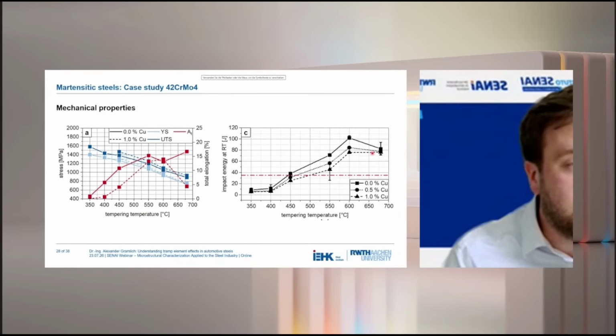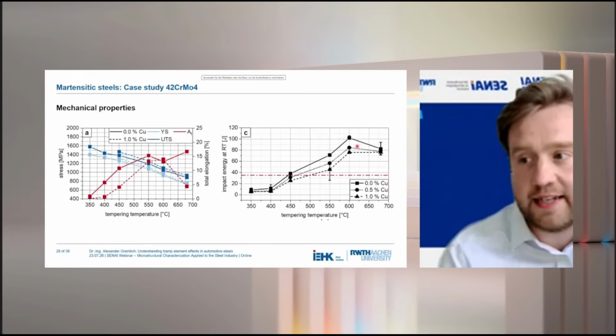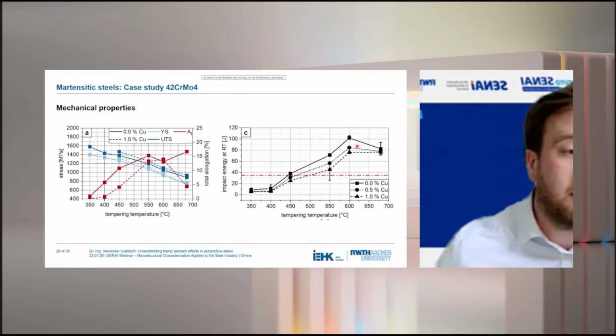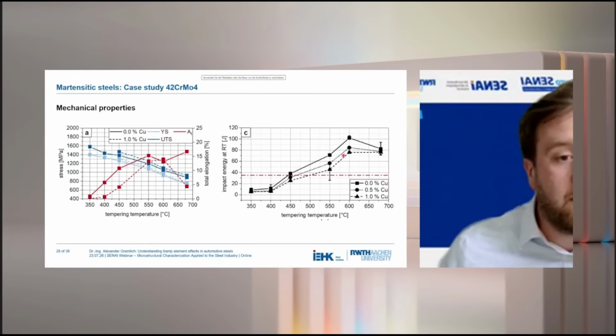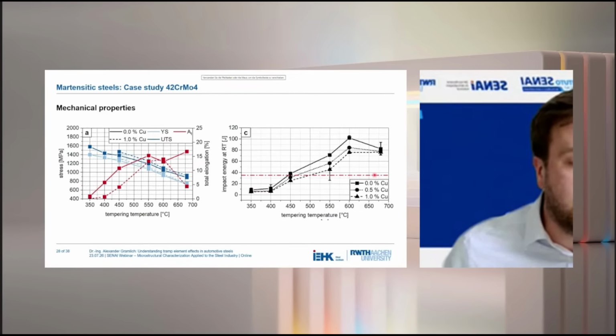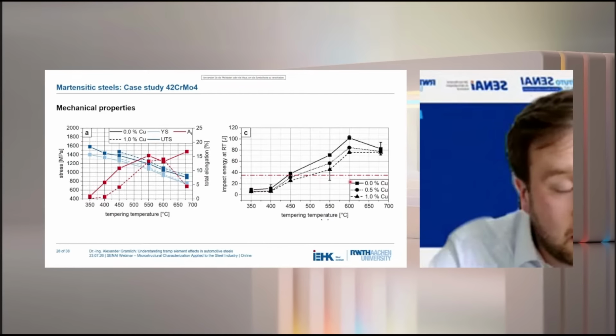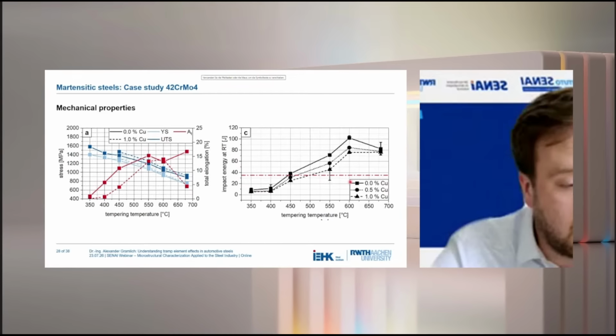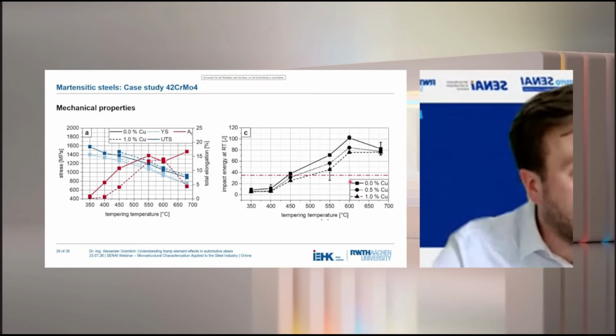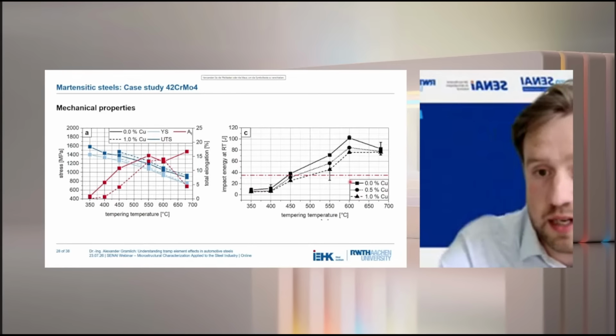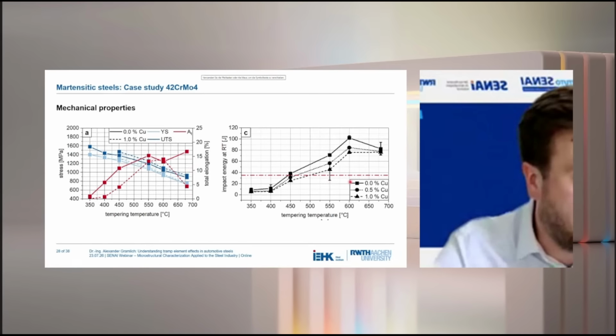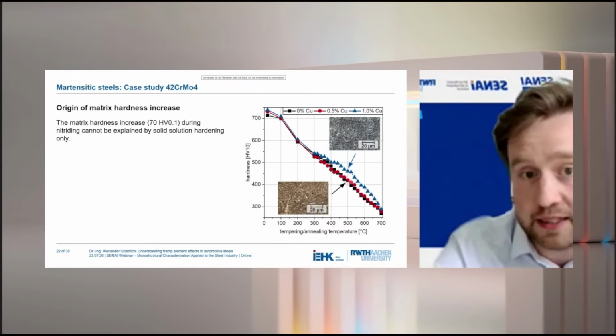We can see that there is a general reduction in this case for the copper alloyed one. However, we are still for most tempering temperatures above the industrial threshold, which was defined here at 35 joules by our industrial partners. So also from these results, I would conclude that even 1% of copper can be tolerated in a 42CrMo4 quench and tempering steel.